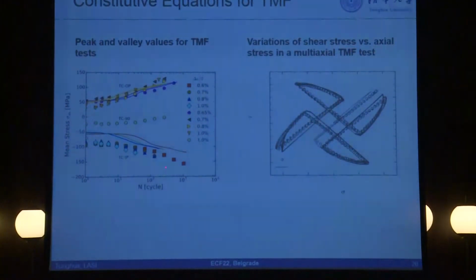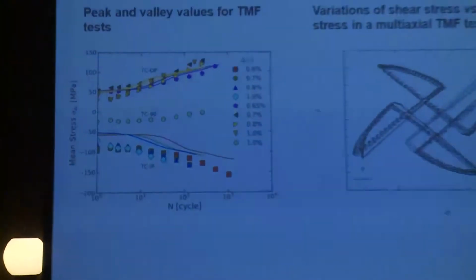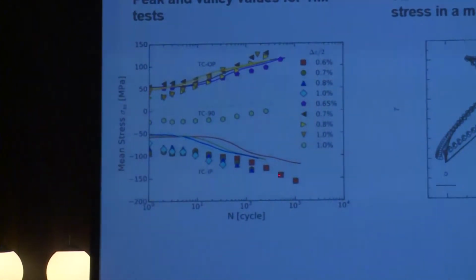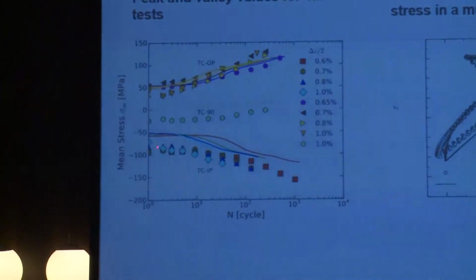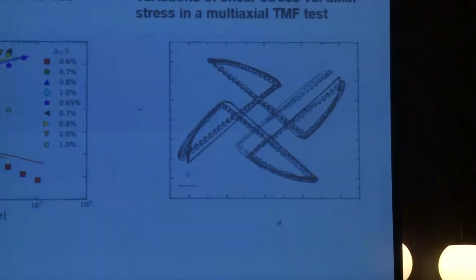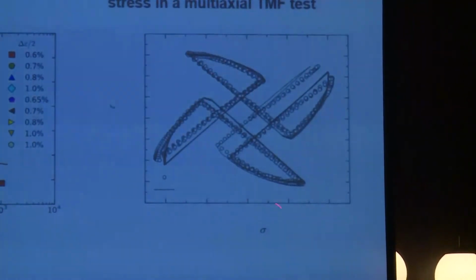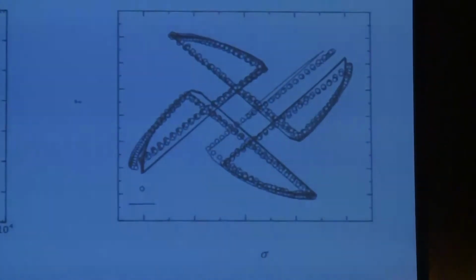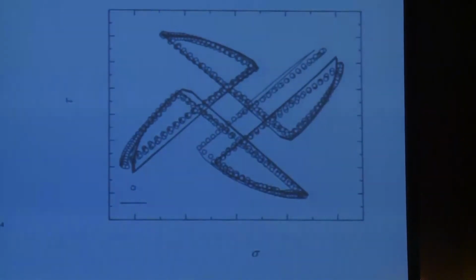actually show us the comparison. Just to show you one example here. More detailed results are published in a recent paper in the International Journal of Fatigue. And you see the comparison of the peak value here between the different tests and results. Symbols show the test results, colors show the experiments, and we have very good agreement. Due to the complex situation, of course, you have a slight difference. You also consider very complex loading cases, stress over strain here. You use the shear stress or normal stress. You see that kind of cross form. It's the most complex situation. The model can characterize this kind of problem.